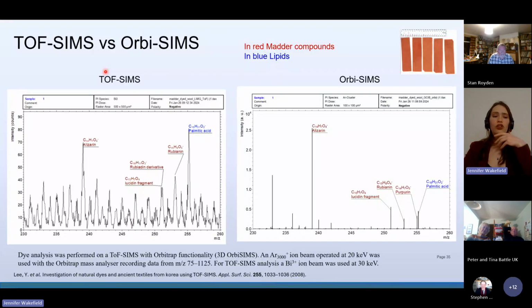So I just want to quickly show you the difference between TOF-SIMS, which has been used before for analysis of textiles, and OrbiSIMS. Like I said, the only difference is really it's a newer mass spectrometer. It's the same as looking at the surface and looking at all masses that are present in the material. But because this is a slightly more modern instrument, it gives you much higher resolution than this instrument. It also has a slightly different mass range. So there are situations where you'd use the TOF-SIMS and situations where you'd use the OrbiSIMS. But for us, this OrbiSIMS is particularly beneficial because it allows us to look at the complexes of dyes and the mordants together, rather than just one or the other.